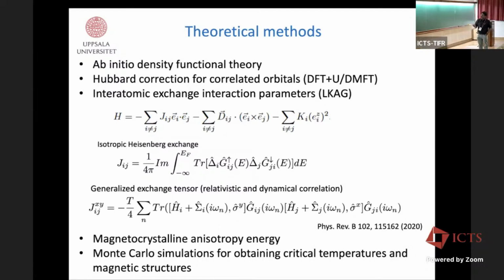Magnetocrystalline anisotropy energy is a quantity which has to be calculated with utmost importance and care, because this is very small compared to the exchange interactions. This number is very small, so one has to be very careful in finding this number. Then when you know all these parameters of the Hamiltonian, you go to Monte Carlo simulations and you go for obtaining the critical temperatures or the spin textures, magnetic textures at different temperatures, what people usually do.